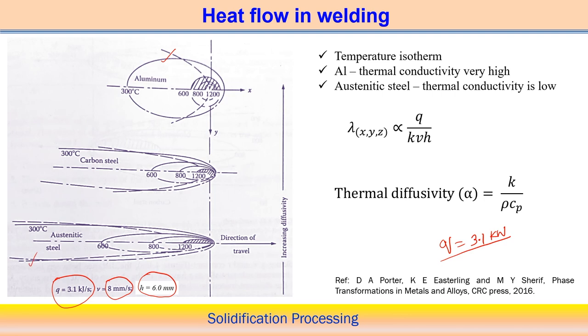In this case, although the welding velocity, thickness of the plate and the total heat input from the arc are the same in these two cases, there is a drastic difference in the temperature isotherm that we can observe here. Aluminum, with high thermal conductivity, has this kind of oval shape, and if the thermal conductivity is very low, we observe an elongated profile. So I mean to say that there is a drastic influence of the thermal conductivity on calculating the temperature profile or temperature isotherm in any fusion welding process.